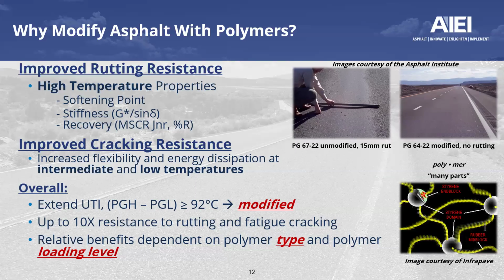All these tests were able to show improved performance of SMA versus dense graded, and an HP versus conventional for the SMA. Just wanted to allude to that. I know there's a lot of effort at the moment looking at maybe a different way of analyzing the data collected by these cracking tests, in a way to capture enhancement due to polymer modification in general and high polymer modification in particular.